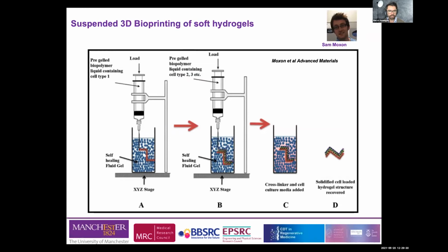Obviously, using hydrogels, it's quite complicated to obtain this precise spatial positioning of the cells. So in order to try and tackle that problem, Sam, who's one of our postdocs, developed a process of additive manufacturing called SLAM, suspended layer additive manufacturing. And what this process allows us is to print hydrogels with very low viscosity, and also with very low stiffness, which allows us to mimic the properties of the brain, and allows us also to do that with very high shape fidelity.